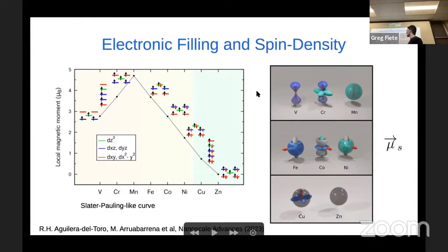We see that it follows a Slater-Pauling-like curve. And well, I cannot go over all of them, but this filling model can give us some insights on the spin density around the transition metals. For example, with vanadium, we see that we have the out-of-plane and in-plane orbitals, ones with both components filled, so something with this shape. And if we go to cobalt, to make a link with the previous part of the talk, cobalt has spin density both in plane, but also some out-of-plane component. Even though the anisotropy is now turned in plane, we will talk about the anisotropy in the next slide, cobalt still has some density outside of the plane. So cobalt once again appears to be a more complex element with a tricky anisotropy.